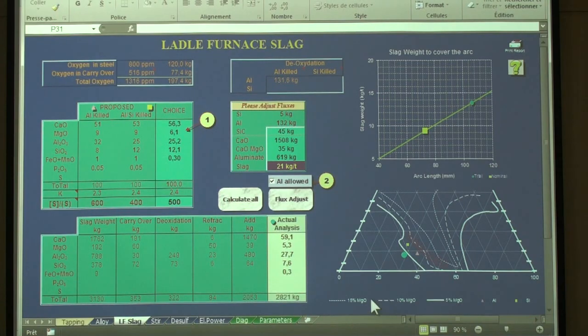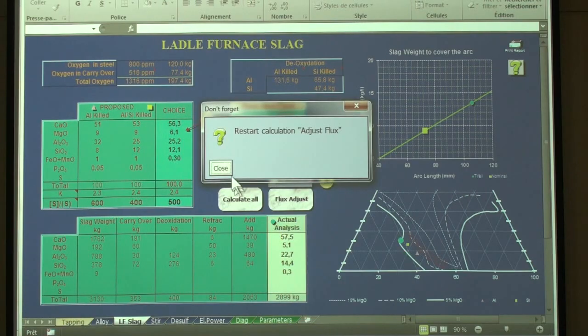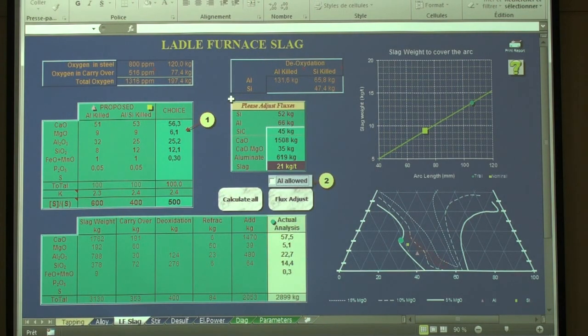in this sheet. So you combine slag analysis and deoxidization, because of course the deoxidization products will go to the slag. Okay? So this is what oxygen we had in the steel. So we have the ppm of oxygen from the steel, which are 120 kg of oxygen. And this is the oxygen fixed on FeO and MnO from the carryover. So this is the total oxygen we have to remove in terms of kilograms.